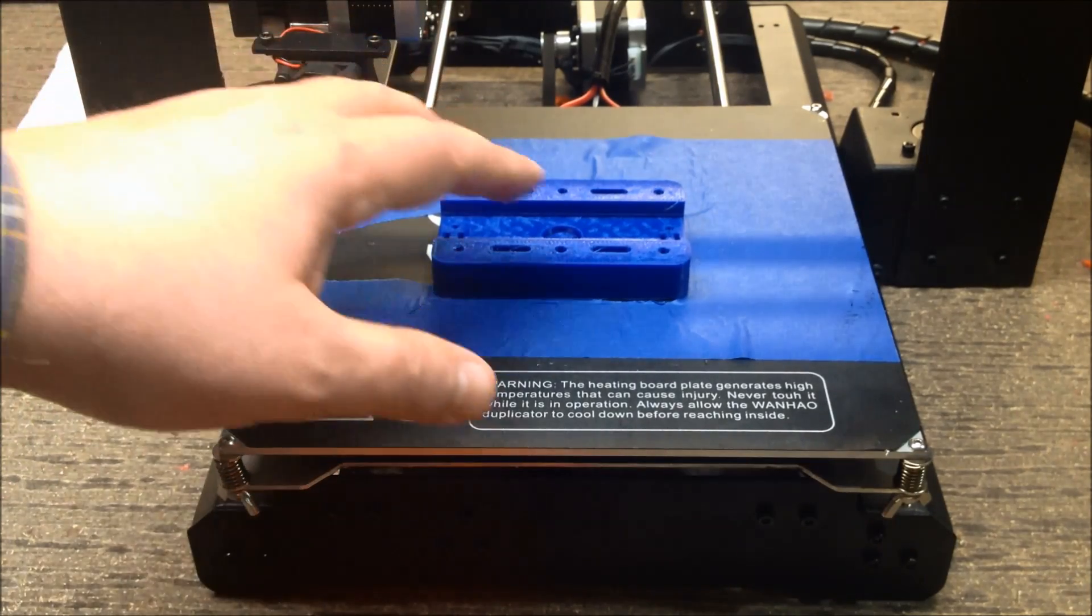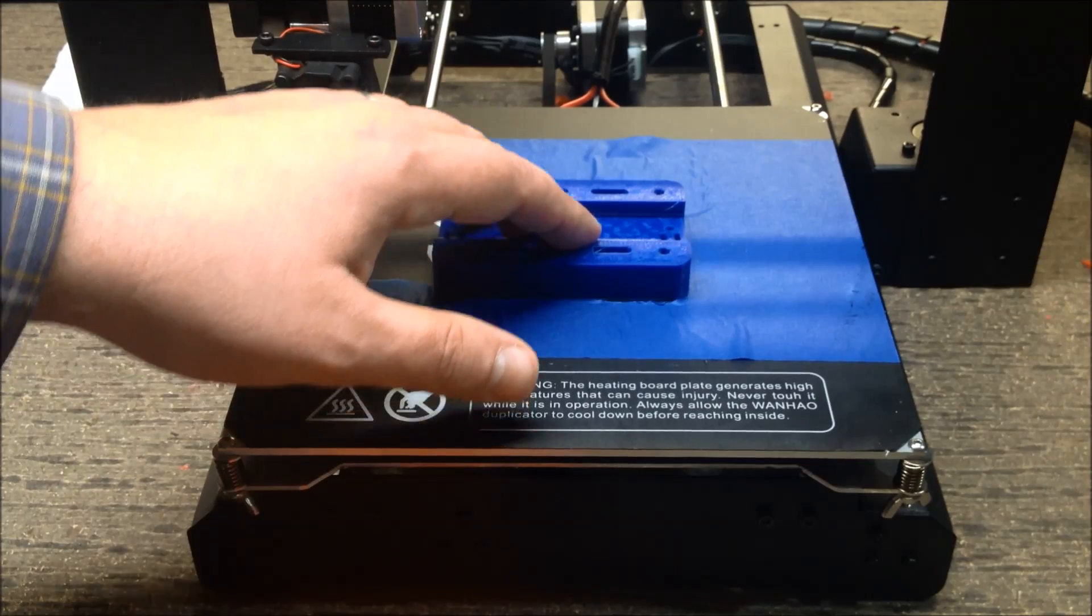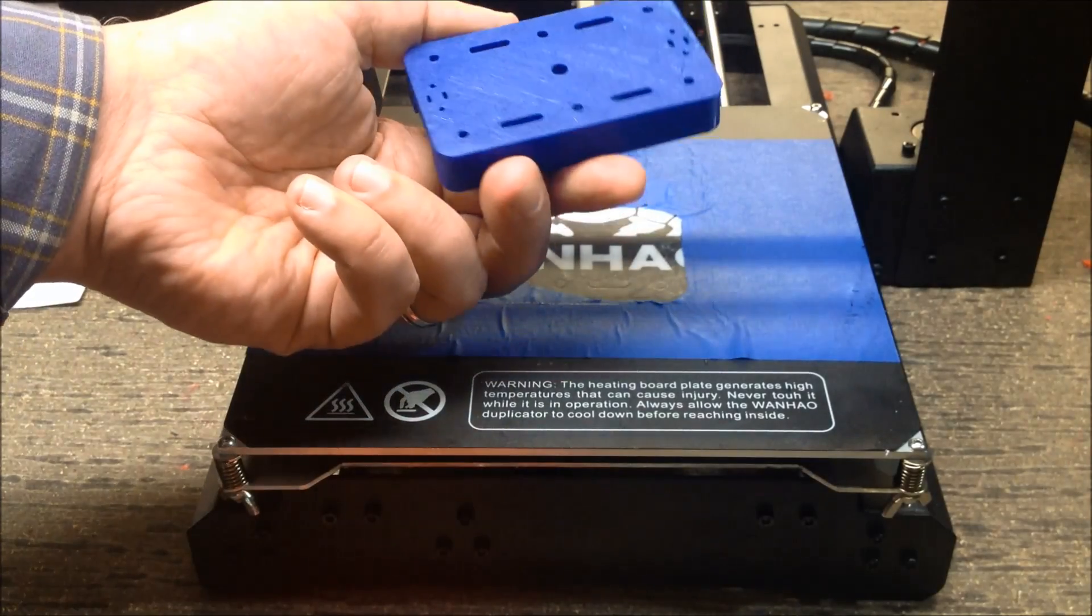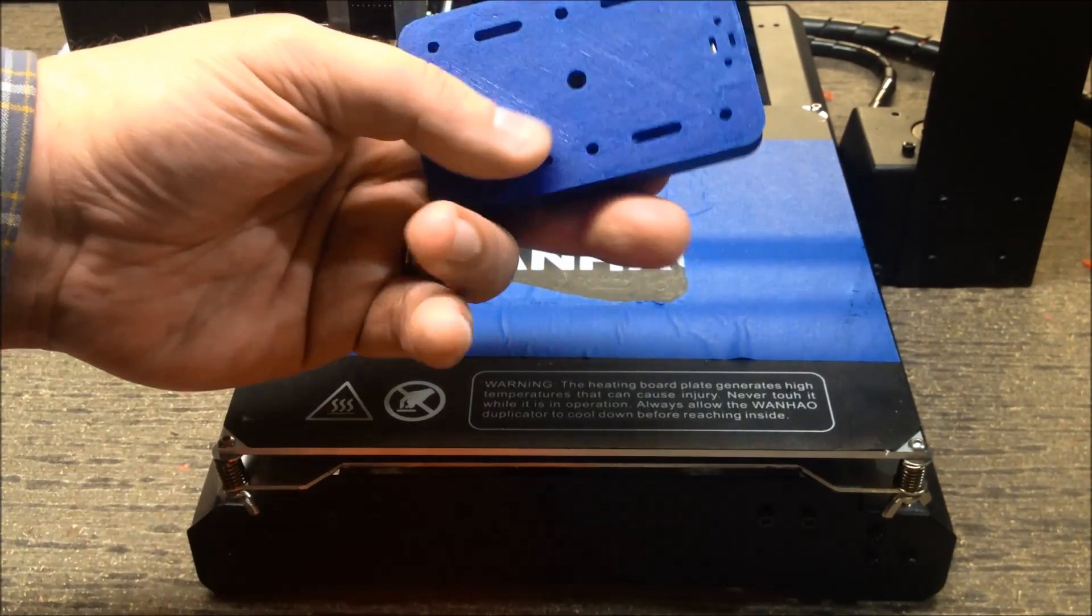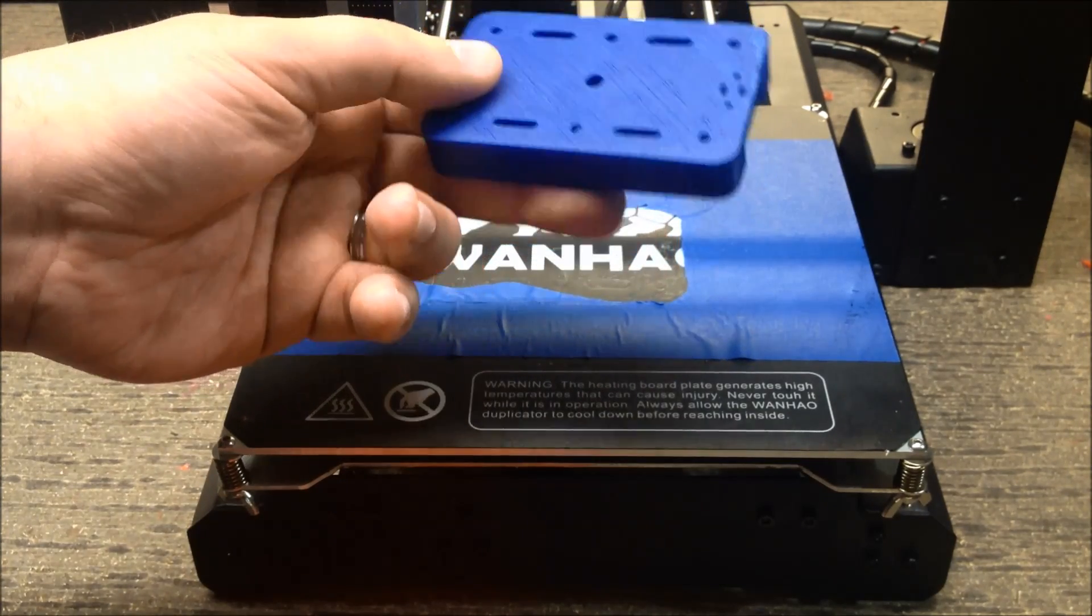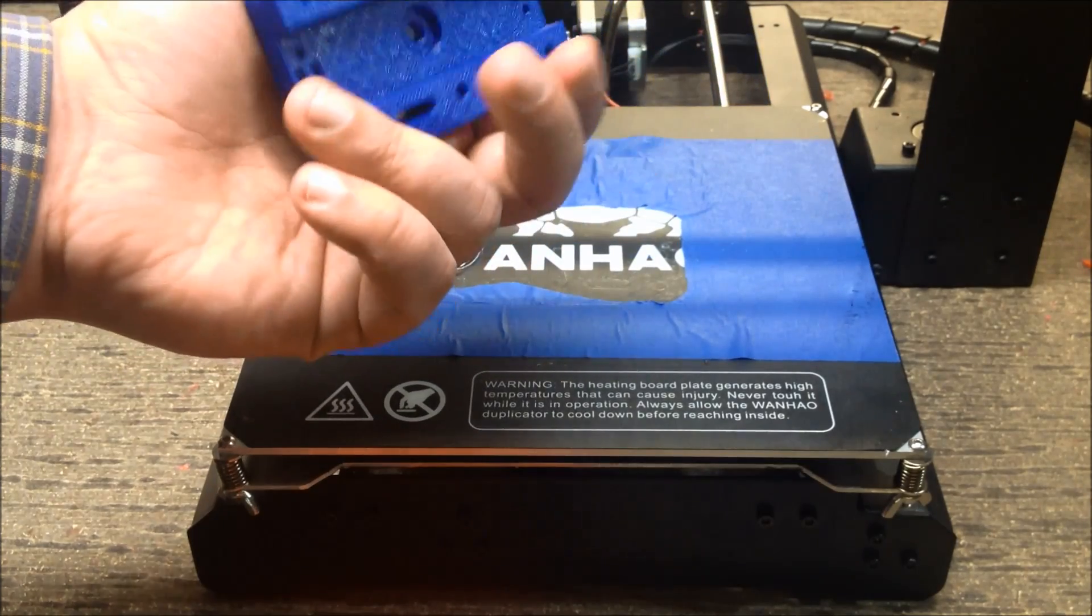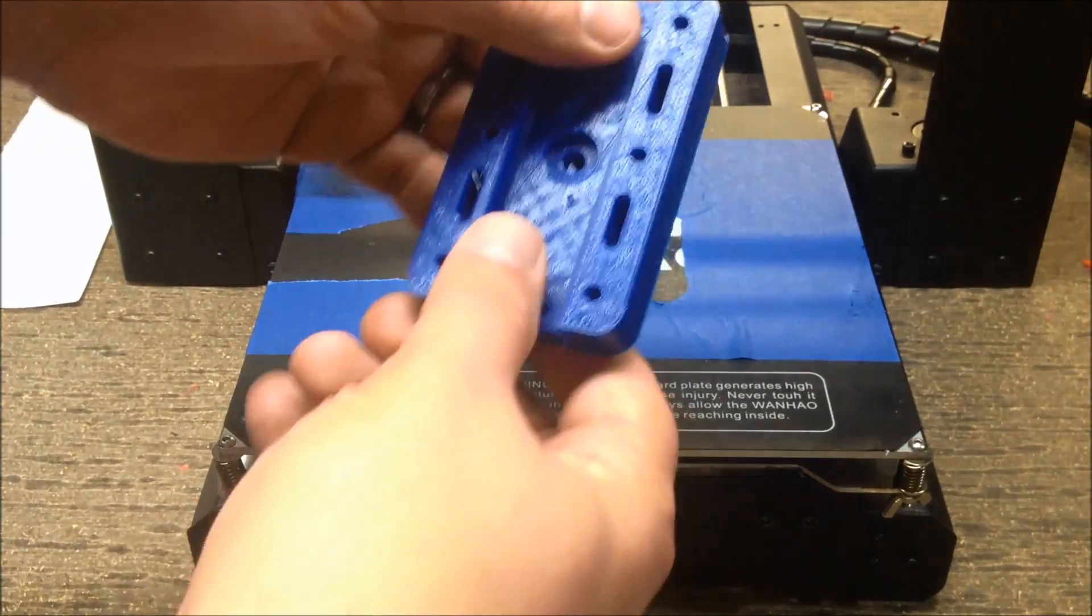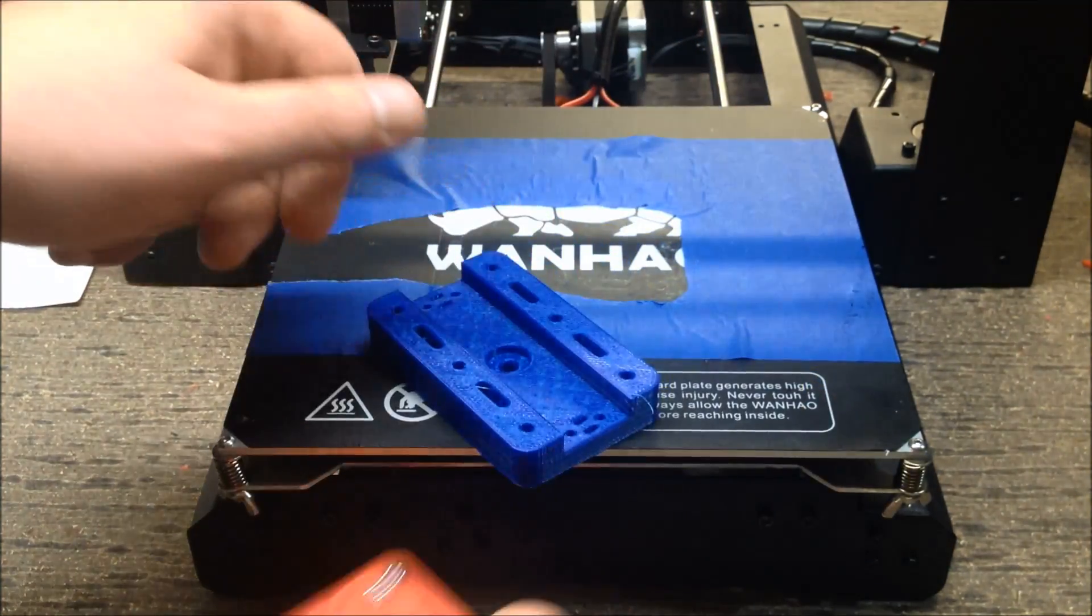From what I've seen on the internet, you really don't need to run a heated bed. I'm going to try some of this without the bed being heated in a later video. But at 90C, this actually came out very nice. No real issues with it. Quite substantial part, pretty strong part.